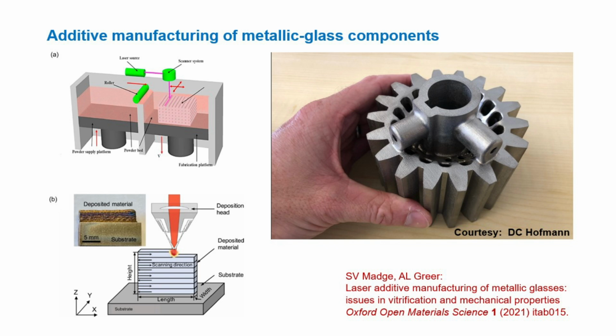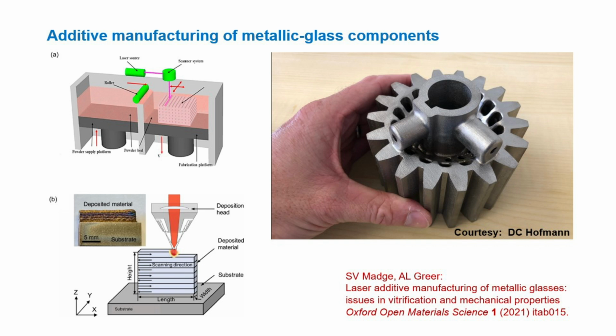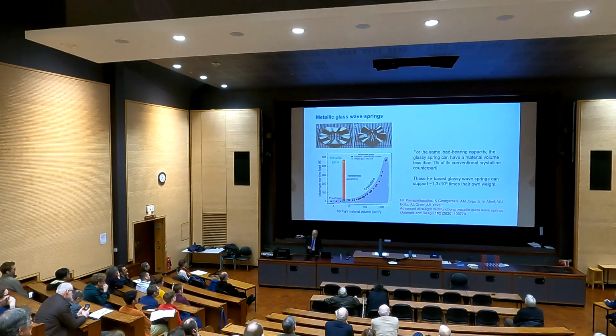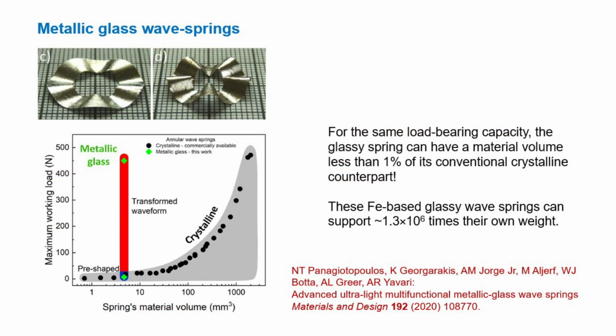But if you can do additive manufacturing, where you build the material up from powder layer by layer, you throw away that size constraint, because every layer is quite rapidly quenched, and so you don't have the link between component size and cooling rate anymore. That opens many doors, but it's fair to say there are many issues with the quality of that material, but very active research area. Those ribbons that you used for the transformer, you could turn into wave springs. You could compare them with commercially available crystalline wave springs. And the fact is that to support the same load, they're just 1% of the weight of the crystalline spring.